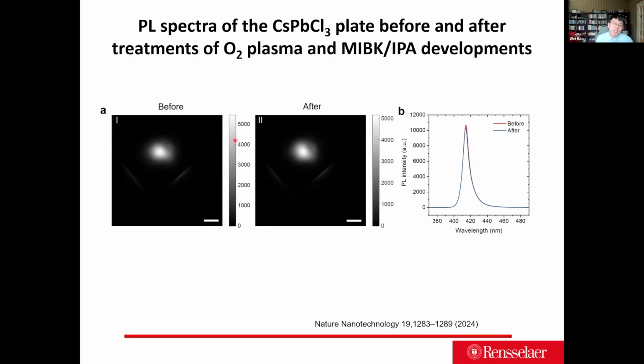Another interesting thing is we intentionally chose cesium lead chloride because, compared with cesium lead bromide, which tends to be optically birefringent, cesium lead chloride is isotropic across the whole wavelength. And, more interestingly, compared with cesium lead bromide, which is more sensitive to nanofabrication, with cesium lead chloride you can optically pump this material and compare the photoluminescence before and after.